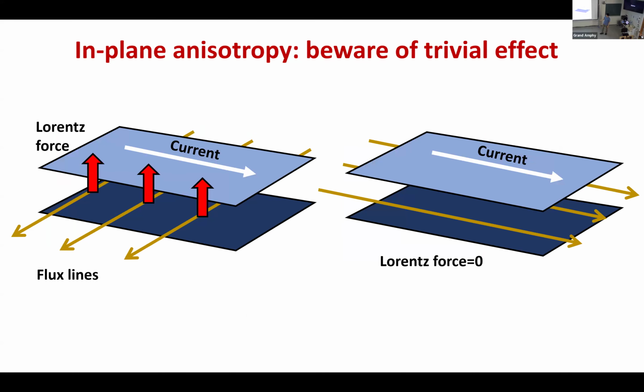However, there's another trivial effect, which people have recently argued. When you apply the in-plane field, even if it's perfectly in the plane, there is a current. You have a sample with a fixed source and drain, and you apply the current. The in-plane field is perpendicular to the current, so you have a Lorentz force on the vortex lines. That Lorentz force may drag your flux lines out of plane and induce some dissipation. If you rotate the magnetic field so that the field lines are parallel to the current, of course you don't have the Lorentz force.